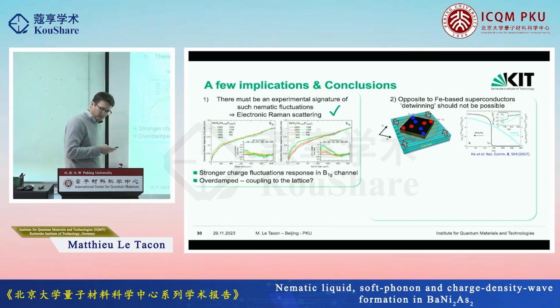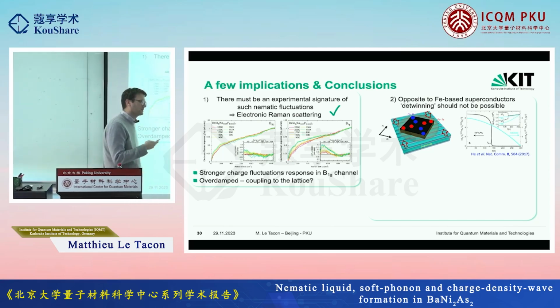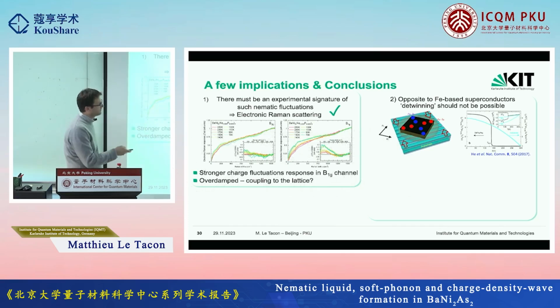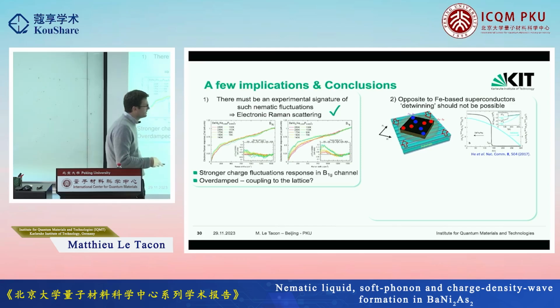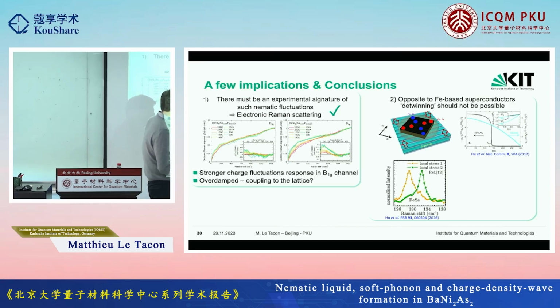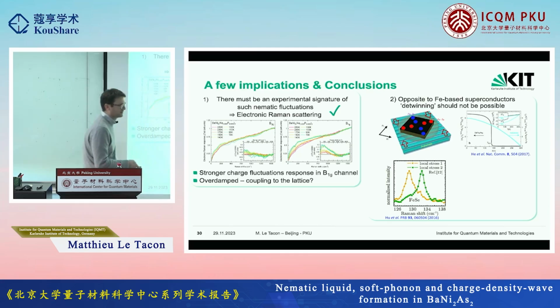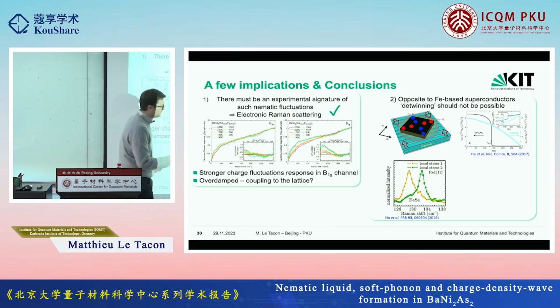What Jörg said is that, well, that should not work in that case, and in particular if you're in the tetragonal phase, because at least if you're in the limit of a small distortion, you should not see an effect. So just to illustrate, these are the data from Yuan that we copied for our paper, and that was replotted by our theory colleagues.